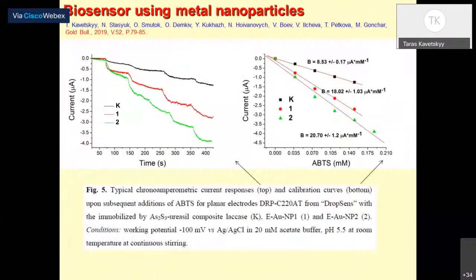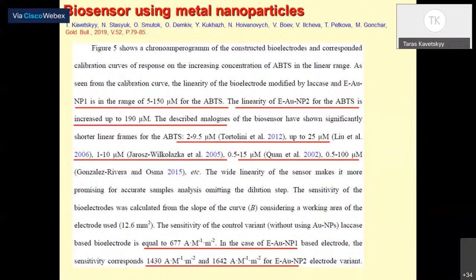And when we compare the pure matrix, this is the As2S3-ureasil composite chalcogenide glass, actually the K matrix, without and with gold nanoparticles, we found that biosensor sensitivity increased with the addition of gold nanoparticles, as was expected. Also, when we evaluate the parameters of our biosensors, we found that we have improved parameters compared to literature data. So we actually constructed the biosensors with the best optimal parameters.